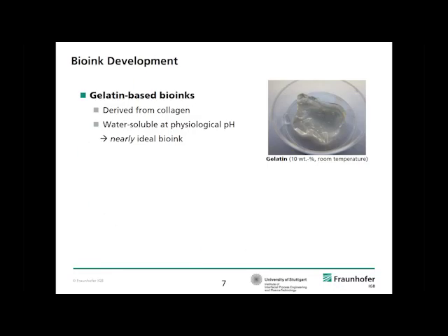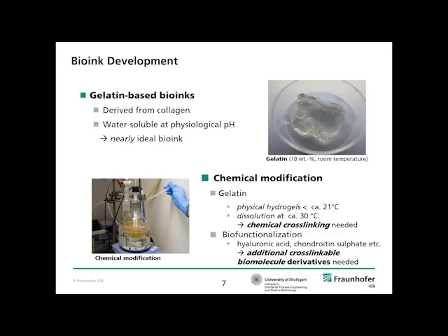A material which is used by many and evaluated currently by many groups is gelatin, as it is a material that is derived from native tissue, from the collagen of tissue, but other than the collagen itself, it is water soluble at physiological pH, and as such it can be used in a solution for printing. But as you probably know from gelatin as a cooking ingredient, the drawback of gelatin is that it forms hydrogels at low temperatures, but it melts at higher temperatures. And as such, it is a solution also at body temperature. And if you want it to be stable, you have to perform a chemical cross-linking additionally to the gel formation.